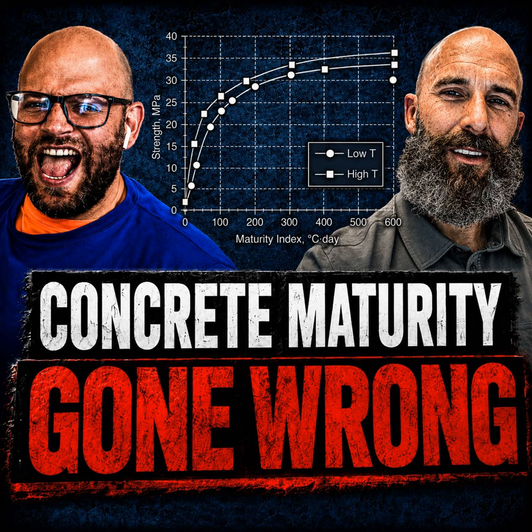For other conditions, and when maximum accuracy of the strength estimation is desired, the appropriate datum temperature can be determined approximately or experimentally according to the procedures in Appendix X1. That's a lot. Well, the first sentence is what matters most. Who has a concrete that has a type 1 cement at a water cementitious ratio of 0.40 without admixtures and a curing temp from 0 to 40 degrees Celsius? It's just...